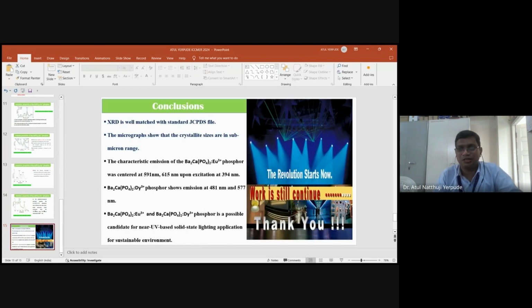Last part is the conclusion of my present work. We find out that this XRD is well matched with the standard JCPDS. The micrograph shows that the crystallite sizes are in the sub-micrometer range. The characteristic emission of the BTS phosphor was centered at 591 nanometer and 615 nanometer. And the Dy3+ phosphor shows the emission at 481 nanometer and 577 nanometer.